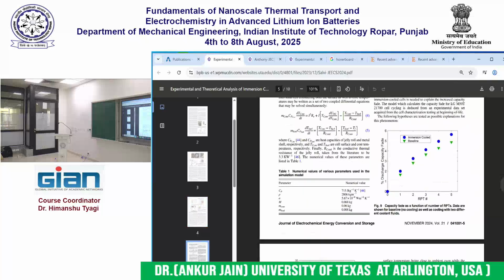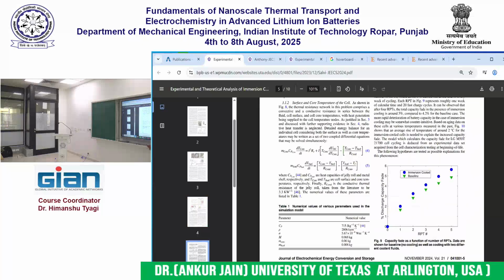And he found that as time passes, there is a reduction in the capacity of the cell as expected. However, the reduction in the capacity of immersion cooled cells was slightly larger than baseline cells that were not being immersion cooled. So our hypothesis was that what is basically happening is that the immersion cooling is working too well. In other words, it is cooling the outer surface of the cell so much that there is a temperature gradient within the cell. The core of the cell is much hotter now than the outside of the cell, because of which it is well known that a temperature gradient in the cell causes greater capacity fade in the cell.